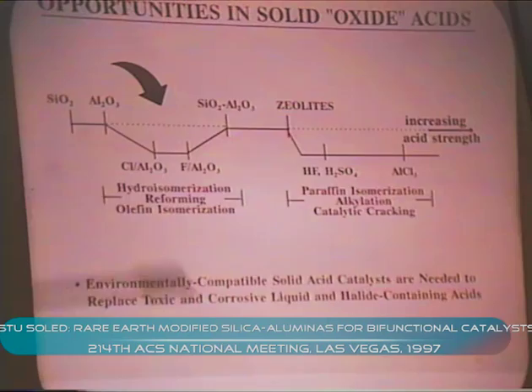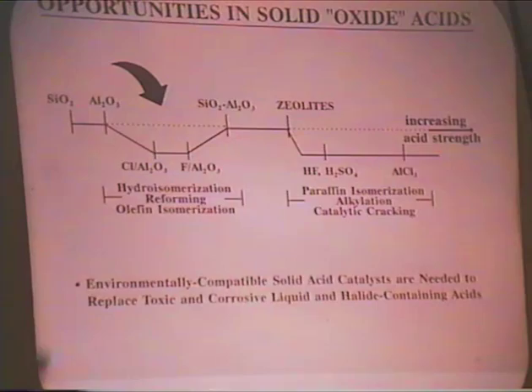Part of our interest was seeing if we could access materials to do reforming without halide on the support. Part of that motivation comes from issues with chlorine being stripped off of the aluminum-containing catalyst during reforming, and the necessity of continuously feeding low levels of organic chlorides to the process — materials that are quite toxic and have come under some regulatory issues.